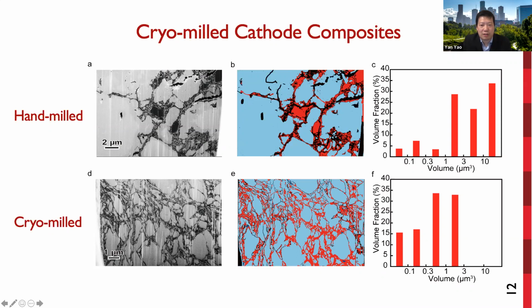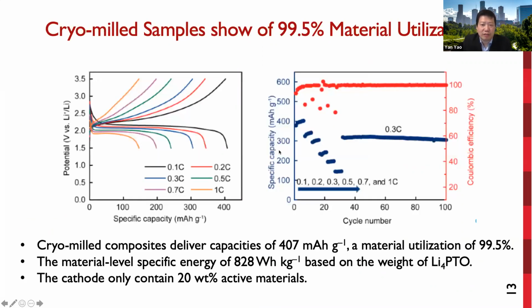From the cross-section SEM images, the black phase is PTO with carbon, and the white phase is the solid electrolyte phase. So we have therefore segmented the SEM images based on grayscale. We see the size of PTO domains for cryo samples is about a factor of 10 smaller than hand-milled ones. Such a significant reduction in the size of the active material contributes to the improved battery performance.